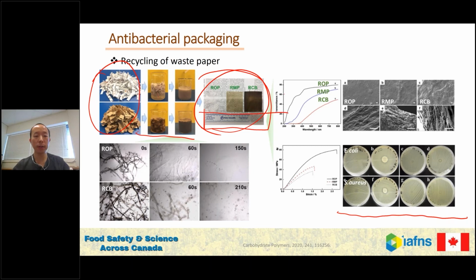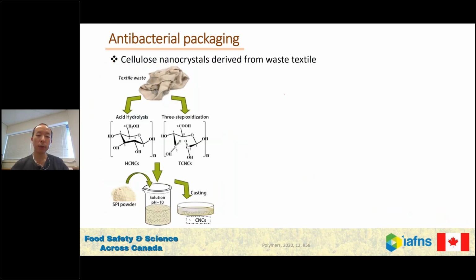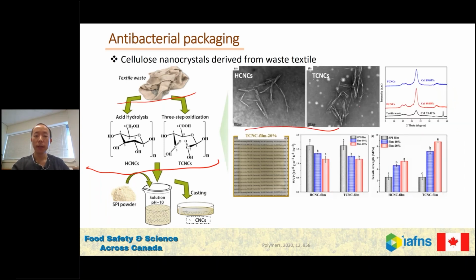That's the first strategy. The second strategy is we use nanocellulose to make antibacterial filler to the packaging materials. So we can use a chemical method to convert the waste material into nanocellulose. And after that, those nanocellulose, they are very tiny. So as I mentioned, the length is about 100 to 200 nanometers, and the diameter is about 5 to 10 nanometers.